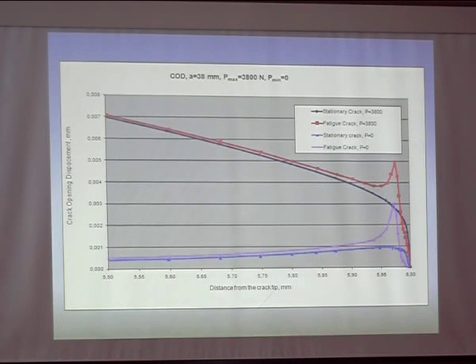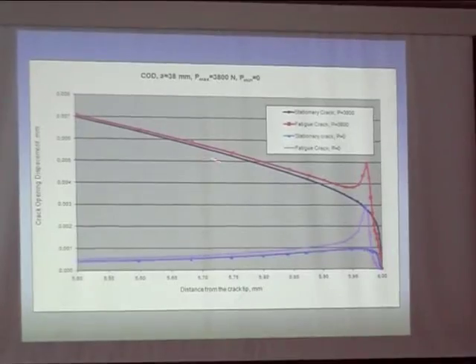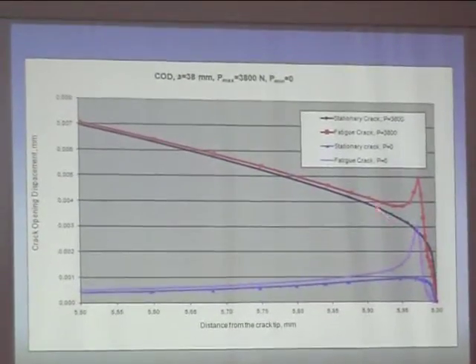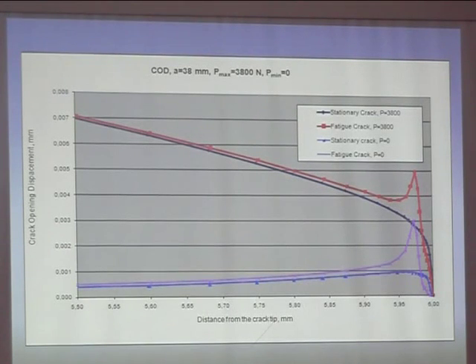Okay. Now, we went to the comparison. I said, okay, let's zoom in a little bit. What you see here is a 0.5 millimeter distance. I did the same calculation for a crack without history, what I called a virgin crack, which was elastoplastic, everything the same, except that crack was not propagated. I only started with 38 millimeters. So this is the displacement field for the fatigue crack, and that one is the displacement field for that virgin crack at maximum load. When we went to the minimum load, again, here is the displacement field at 0 load of the fatigue crack, and this is the blue, the virgin crack.